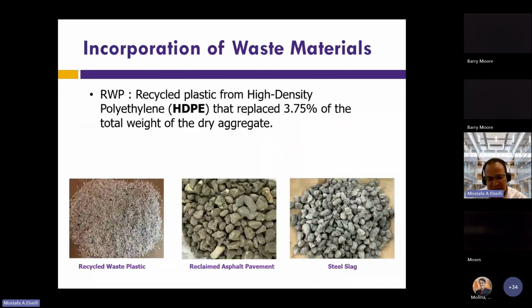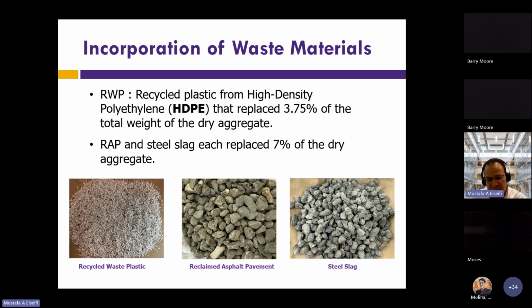So the additives that we used: we used recycled plastic waste. You can see it in the picture here. It's a high density polyethylene, and we used it at a content of 3.75% of the total weight of the dry aggregate, which again, in OGFC, has not been attempted before, so it was something new for us. The reclaimed asphalt pavement, or RAP, you can see it in the picture here. We use it at a content of 7%, and we also use steel slag at 7% of the dry aggregate.